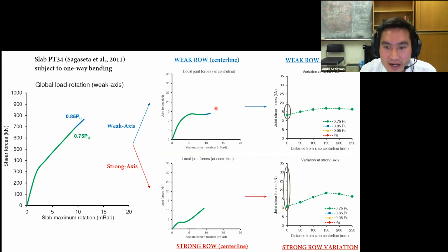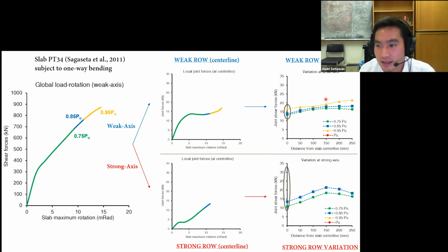At 85%, we still have a normal increase in here, and also in the strong axis, it is still a normal situation. At 95%, we have a higher increase in here. But now the most interesting part happens between 95% and 100% of the failure load. We see we have a flatter response in here, which indicates a typical shear failure at the end.